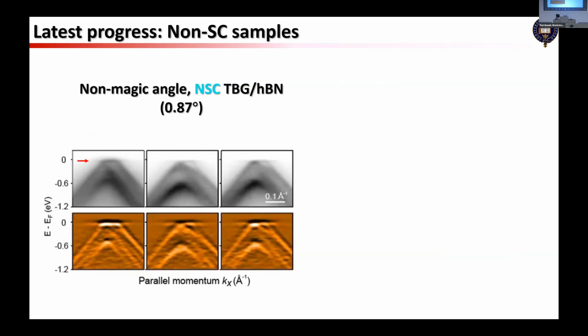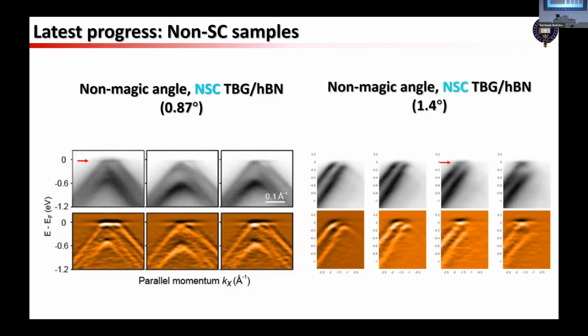And what about the non-superconducting sample? The previous one addresses the repeatability of this flat band replica, and this one is to study the correlation with superconductivity. So in this way, we kill the superconductivity by different methods, right? It's not aligned with the HBN, but we just change the twisting angle. And although you can see there are still flat bands here, you don't see this replica anymore. And if we just crank up the twisting angle, we don't see the replica either. So you can screw up the superconductivity either by aligning it with the substrate, or by changing the twisting angle. And if the superconductivity doesn't show up, then we don't see the replica. So that means the replica occurrence and the superconductivity have a pretty strong correlation.